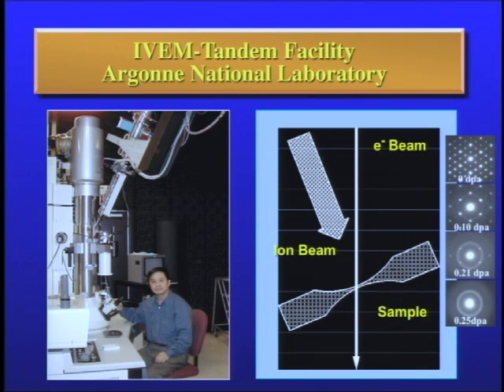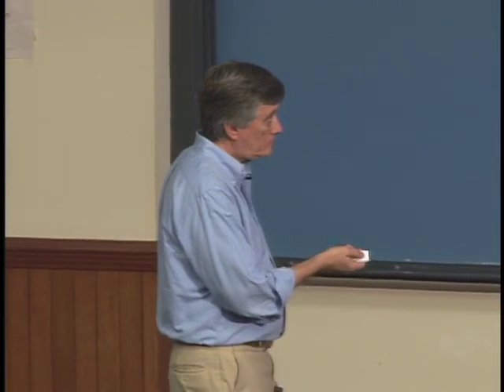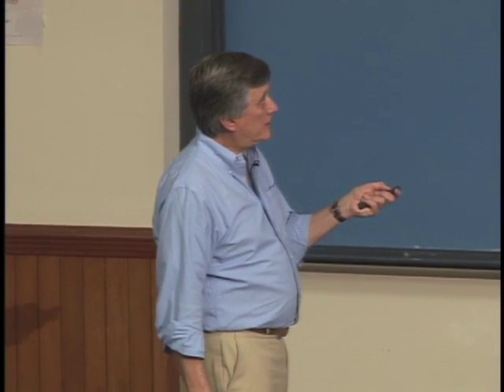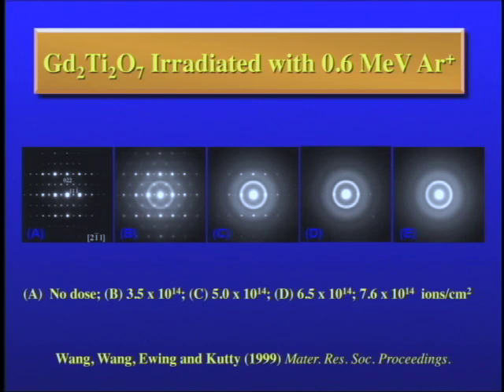So we have also then 3 types of data, 3 very different experiments describing the damage. And taking a series of selected area diffraction patterns, you can see the transition from fully crystalline to fully amorphous. And with the gadolinium titanate, if you've retained your crystallography, if you ever had it, looking at the diffraction maxima, you'll see from here to here we're missing some spots, and this is pyrochlore, and this is the disordered defect fluorite structure. So the gadolinium titanate disorders, survives for a little while, but at higher doses it becomes amorphous.